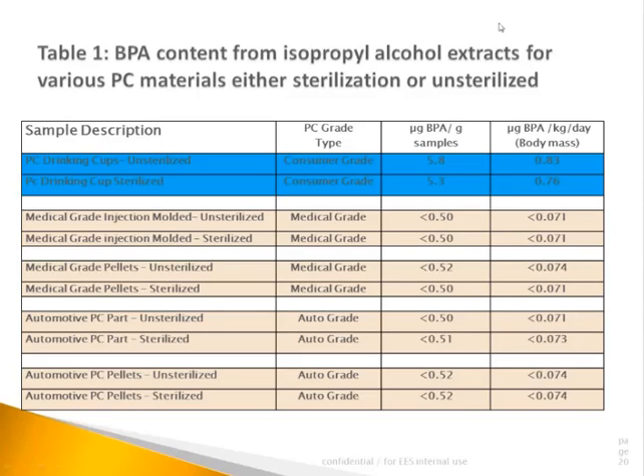The IPA extraction results indicated, with the exception of the drinking cups, which is the consumer-grade polycarbonate, BPA concentrations were well below the level of detection. This was evident from the rest of the data. In fact, the amount was less than 0.5 microgram per gram sample. BPA found in the drinking cups was 5.8 microgram BPA per gram for the unsterilized condition versus 5.3 microgram BPA per gram sample for the sterilized equivalent.